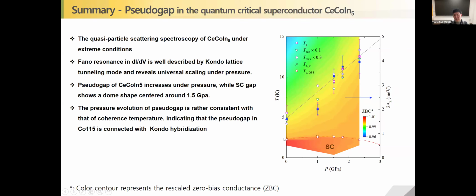I mean, as you can see, the superconducting gap and superconducting Tc have a dome, which is a peak around 1.5 GPa. On the other hand, the pseudogap size just increases. And this clearly shows that the pseudogap feature in CeCoIn5 is not related to the preformed Cooper pair phase or the superconducting state, but rather follows the trend of the so-called coherence temperature and the appearance of the Ce 4f itineracy, indicating that this pseudogap feature is related to Kondo hybridization.